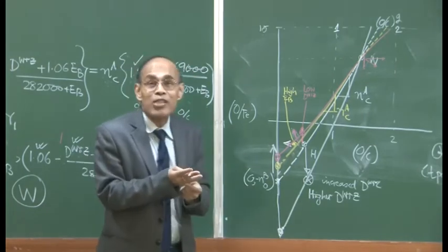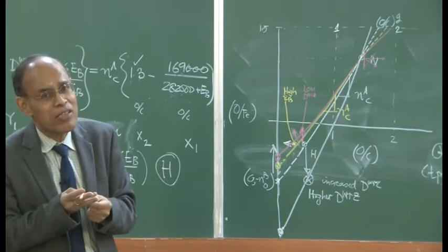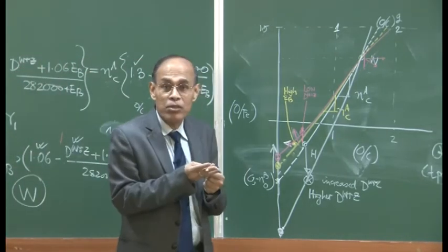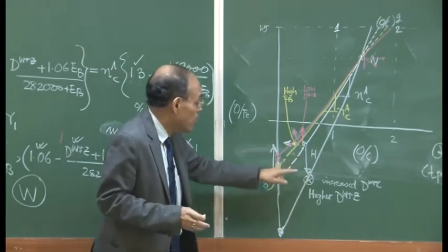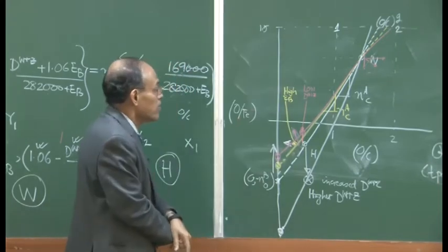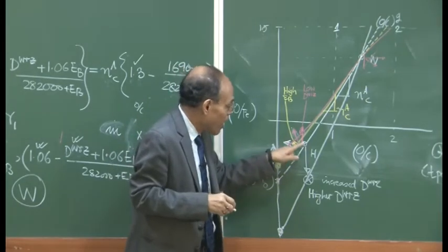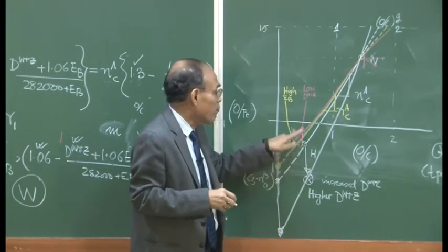So, a bigger blast furnace, relatively pre-processed ore which does not contain much impurities, and a good quality coke, for example, are prerequisites for moving this point H in a positive direction. I have said enough about what will drive this point to an unfavorable location and what will drive it to a favorable location.